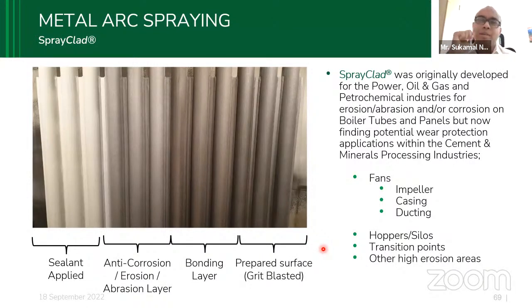I think we all know that the major problem with a boiler tube panel is that the panel gets burst because of the high ash, or it gets eroded from outside, becomes thin, and during operation it bursts. Because of this spray cladding, a very fine micron surface coating we apply from outside, it protects the life of the boiler panel and enhances the life of the entire component.